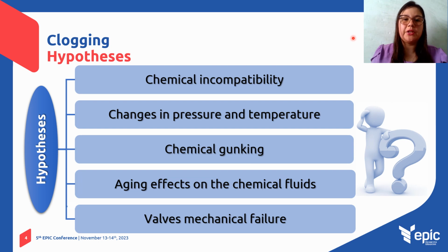According to the clogging observed in the chemical injection valves, some hypotheses can be raised about this problem. Maybe there is no chemical compatibility between the flushing fluid, the glycol or the butylglycol that is used in the Peregrino basin as a flushing fluid and a hydrate inhibitor in this chemical injection line, and the emulsifier that is a polymeric surfactant, which is a block polymer with ethylene and propylene oxide groups diluted in ethanol. And even there is no chemical compatibility between these fluids and the clogging material.